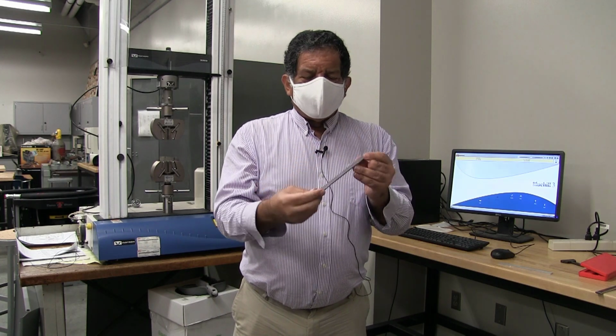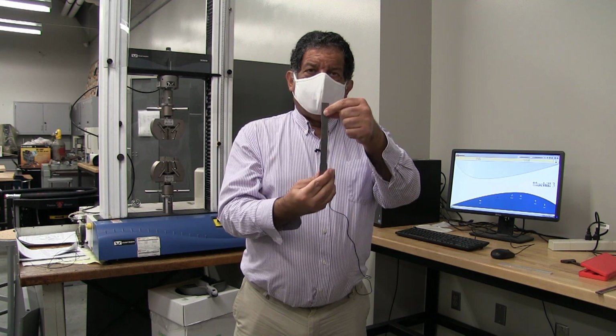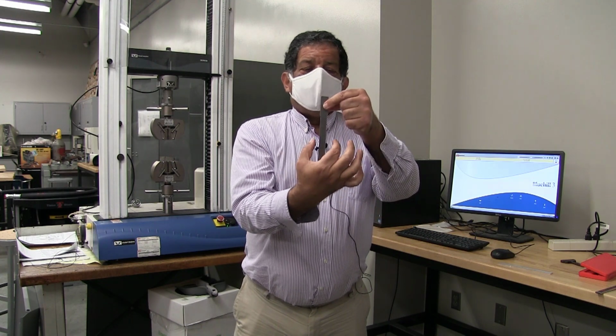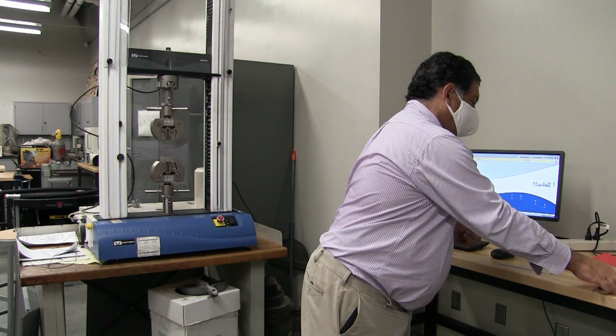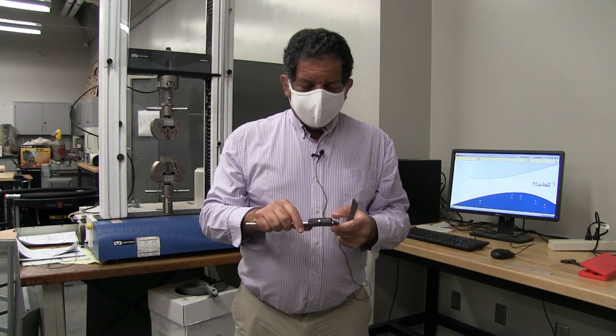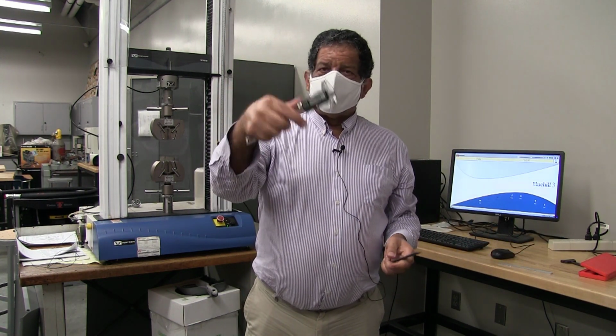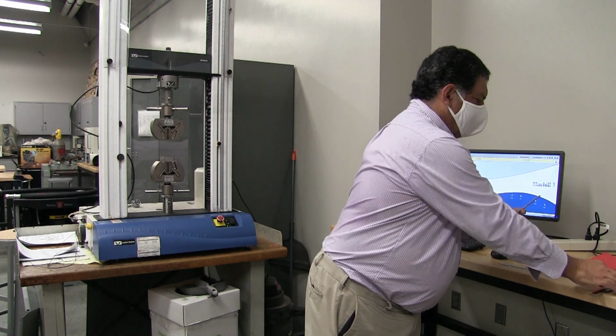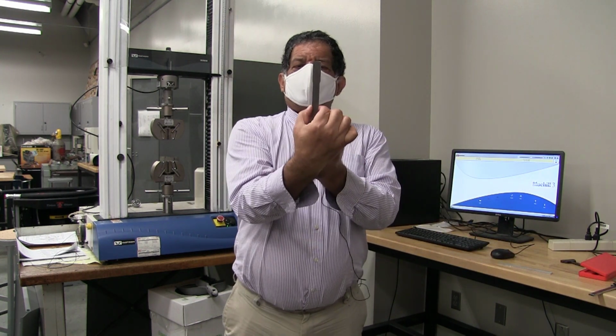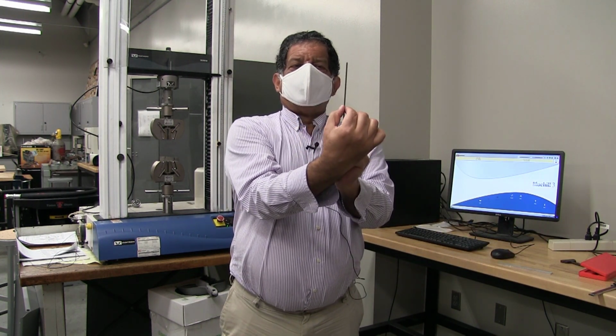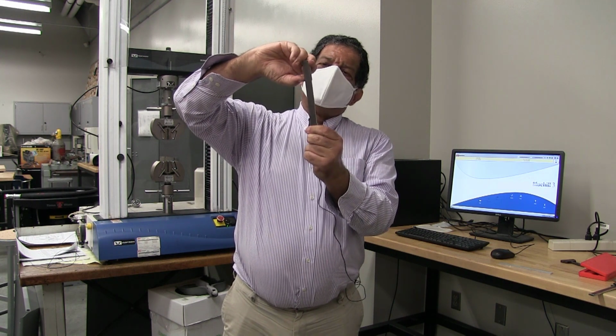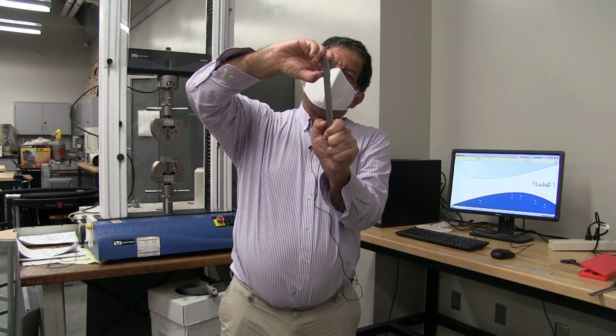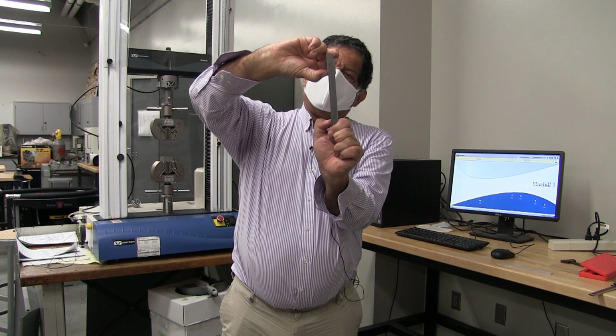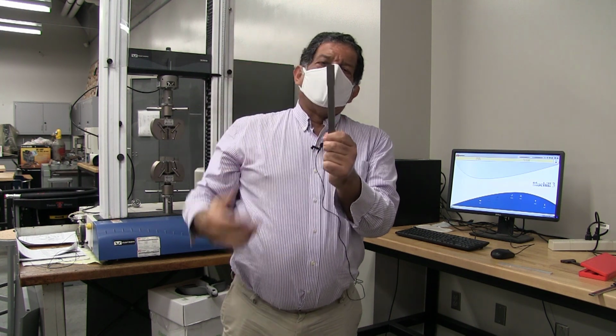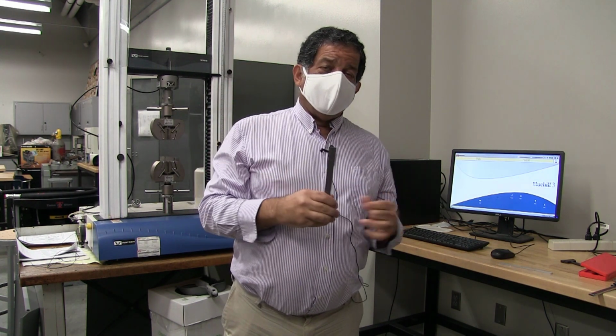So what we're going to do is measure the dimensions of the specimen. We're going to use a pair of digital calipers over here, and we're going to measure the width of the specimen, the thickness of the specimen, and the separation between the two fillets, which is the total gauge length of the specimen. And those we're going to enter into the machine.